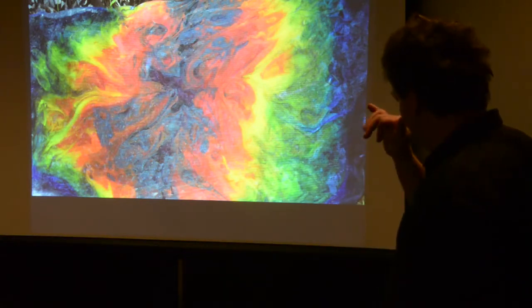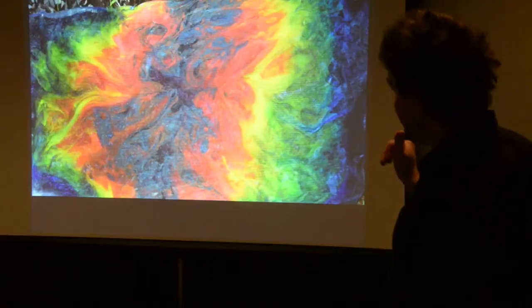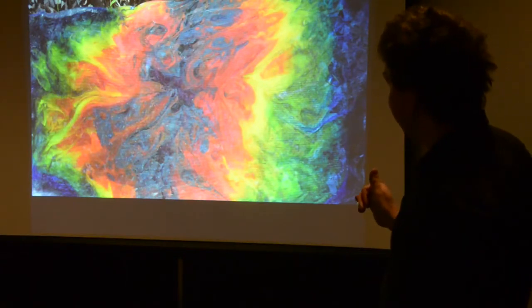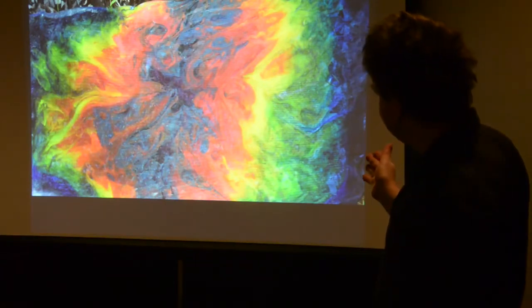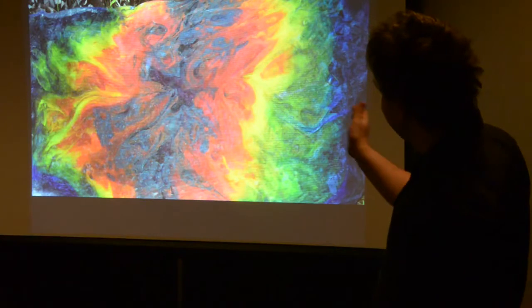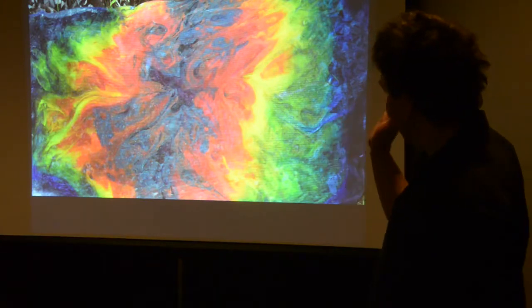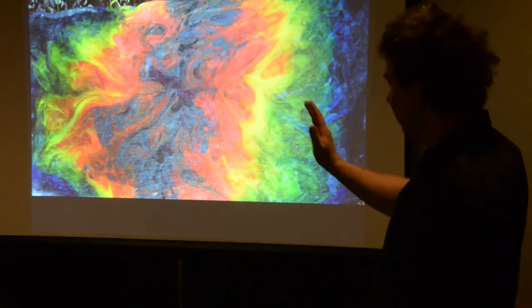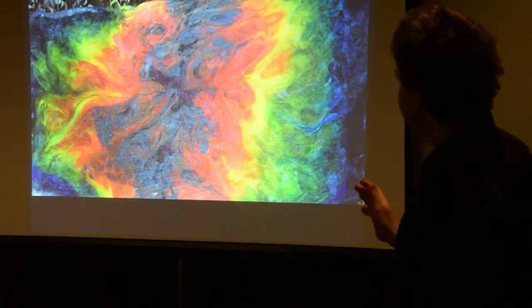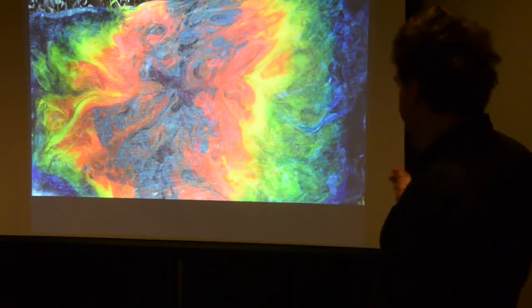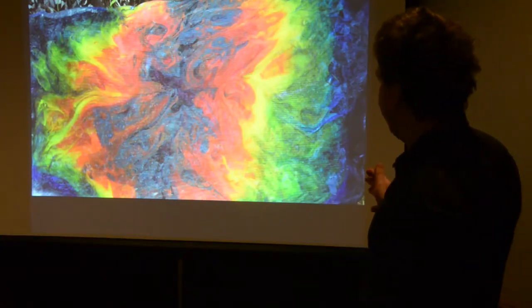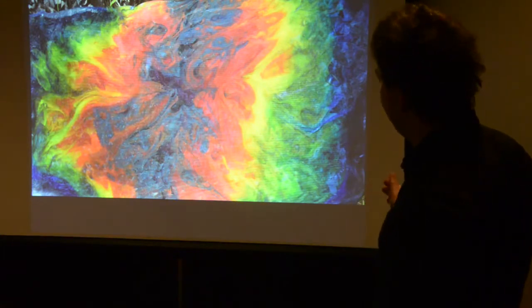Greens, you're going to use chromium mostly. Greens and yellows are a big incompatibility. This is a sheet of stained glass I had done, and to get that green-yellow mix, I'm actually doing casing. I'm putting a layer of clear glass as a barrier between the green and the red, because the chromium will interact very negatively and create one of those dark, opaque browns that you don't want to see.